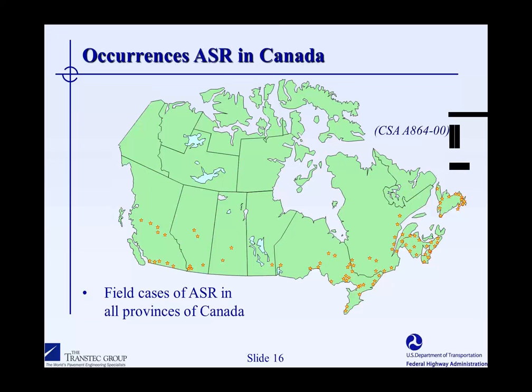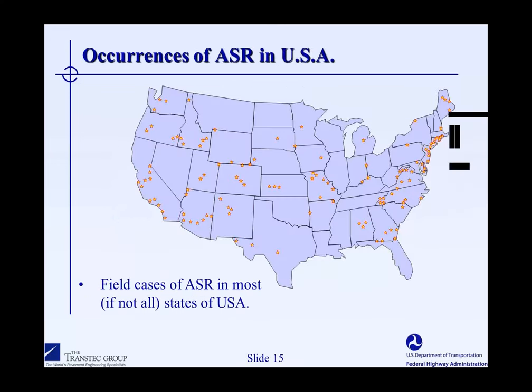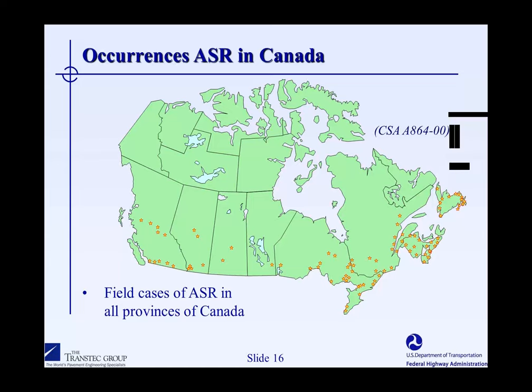Similar situation in Canada. Actually, before I go on there, it's interesting to note that even though ASR started in the West, there seem to be more cases in the East. And I think this is partly a reflection of the fact there's perhaps a higher density of infrastructure in the East. But it's also due to the fact that historically the alkali contents of the Portland cements have been higher in the East than they have in the West, and I believe that's still the case.